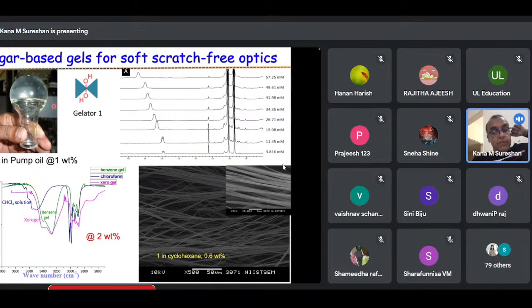So this is an example of a gel we have made in an RB flask using a particular gelator, which I have shown the structure. This is from mannitol, actually. So this is a sugar-derived material. So this is in pump oil. And it's at 1 weight percent. That means there is 1 gram in 100 ml of this oil, actually. So 1 gram of material can gelify at least 100 milliliters of this particular oil, pump oil.